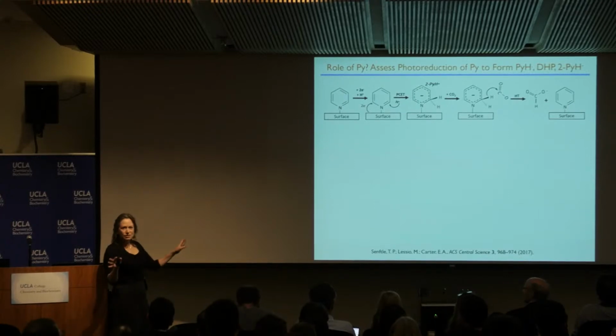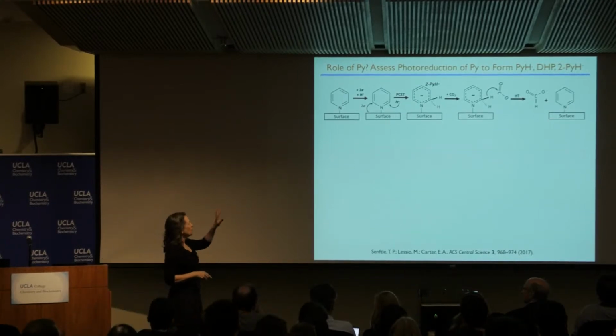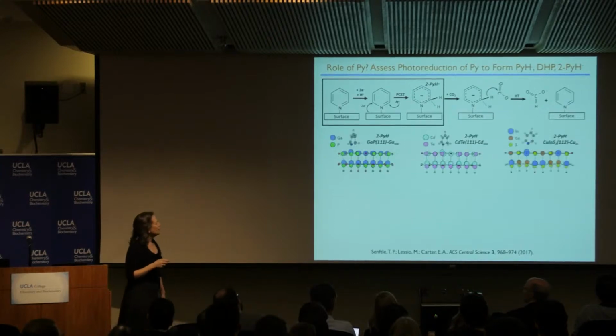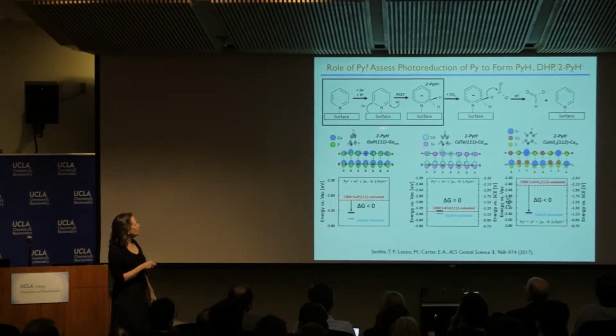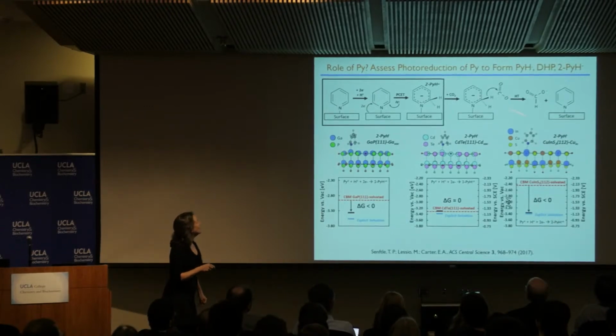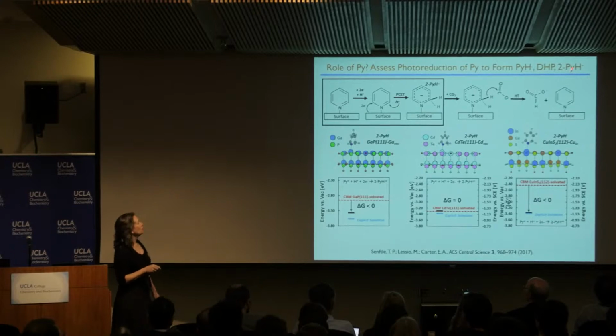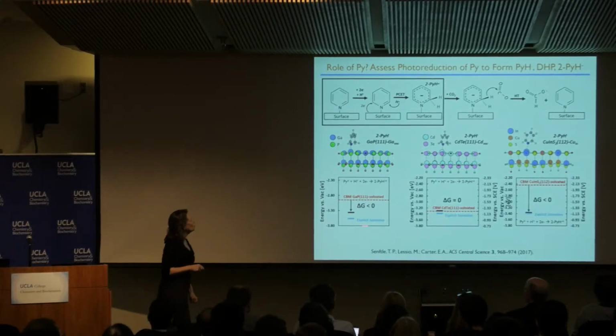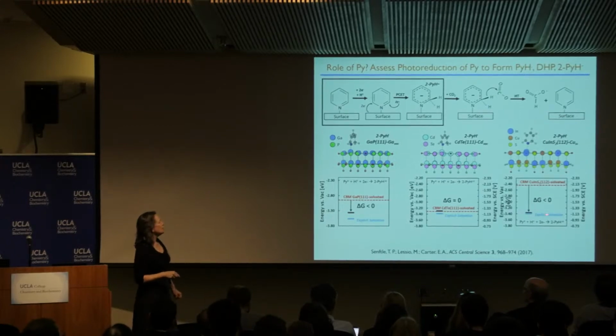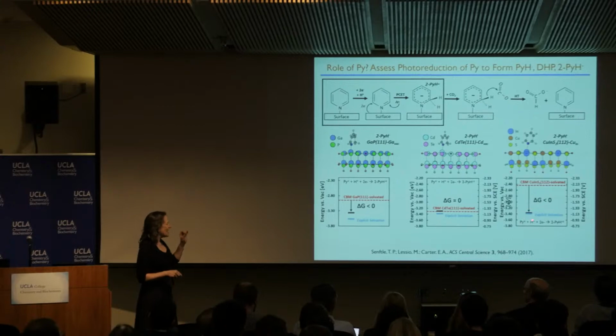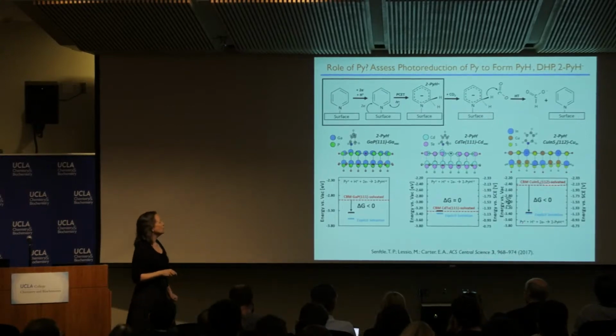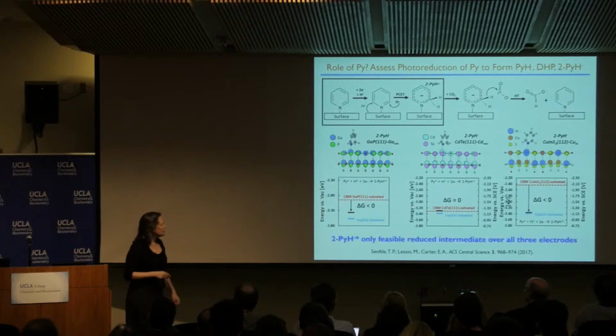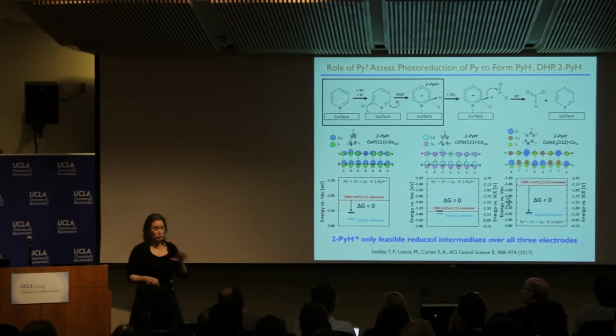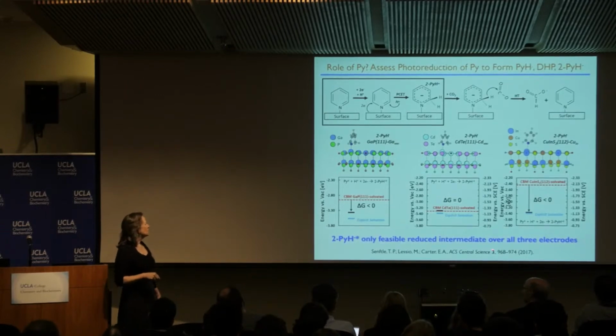And so I could give a whole lecture on that. I'm not going to do it. I'm going to tell you that in the end, what we found is that the one species that could be reduced on gallium phosphide, cadmium telluride, and copper indium sulfide is in fact 2-pyridinide. And that's shown by these conduction band minima in red, and the reduction potentials are shown, the most accurate calculation in this light blue. It is, as it should be, below the energy of the electrons that are photoexcited. So this is the only feasible intermediate. We knocked out all the others that could possibly be playing a role over a period of years.